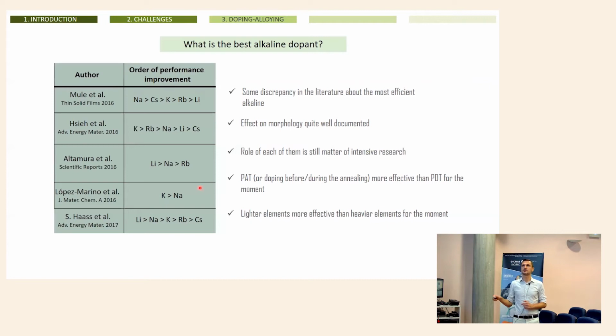Okay, and this is quite similar to CZTS. Then we started to work with these alkaline elements. Alkaline elements play different roles on kesterite. I wouldn't like to extend too much because it would require hours to explain alkalines in this system, but basically what alkalines do is first to improve the crystallization, because you used to form crystallization fluxes with sodium and selenium, then the temperature required for a very nice crystallization of the material is much lower than normal. And the second helps to control the conductivity of the material.